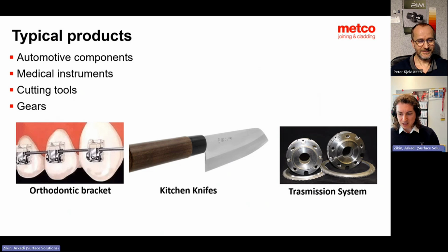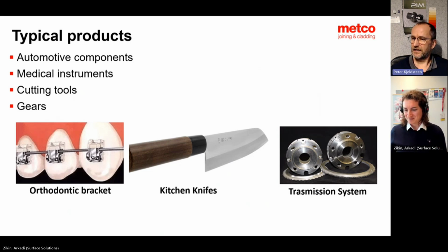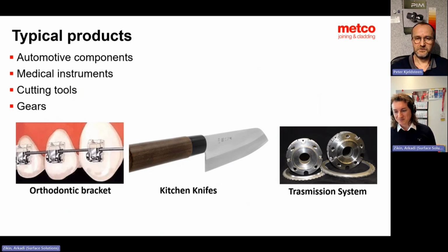And then at the end of the day, what I found very interesting is the most expensive kitchen knives. They're made from high-speed steels, made by powder metallurgy, because they get the highest hardness and extremely long lasting times, maintaining sharp edges. And some of these knives are even made in a Damascus design. So when this is HIPed, hot isostatic pressed, you take powder into a big steel can, and you put that into a hot isostatic press where it's heated to above 1,000 degrees and pressed with 1,000 bars. And if you in your design take two different alloys and position them like that in the powder shape, and you press it, then you have the look of a Damascus steel.